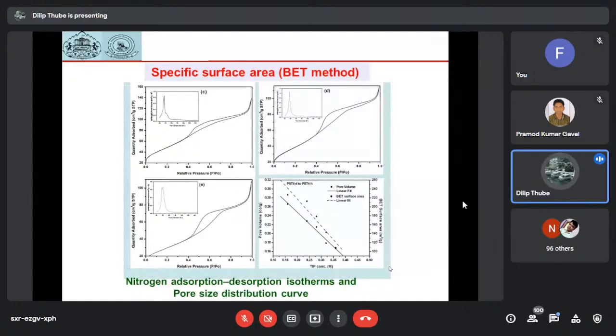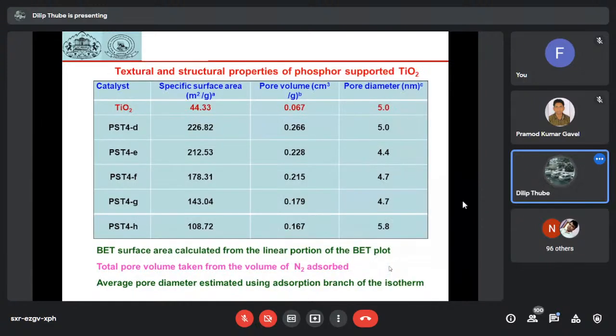And this slide shows the nitrogen adsorption and desorption isotherms, which clearly indicate that the surface area of the nanoparticles is improved. So the textural and structural properties of the phosphor-supported TiO2 material, which are evaluated by using this BET method, are mentioned over here. Various materials have been prepared.